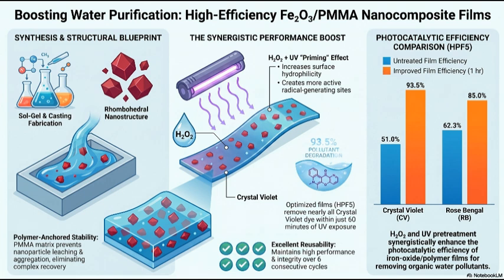When the UV light hits the iron oxide, the holes left behind in the valence band react with the water molecules and hydroxide ions that have now flooded into the plastic matrix. This specific reaction creates hydroxyl radicals. Hydroxyl radicals. I've read those are some of the most ruthless oxidizing agents in nature. They are entirely uncompromising. They are highly electrophilic, meaning they aggressively seek out electrons. They attack the electron-rich double bonds within the dye's molecular structure, which, incidentally, are the same bonds that give the dye its vibrant color. Oh, that's wild. So it literally bleaches the color out as it destroys it.